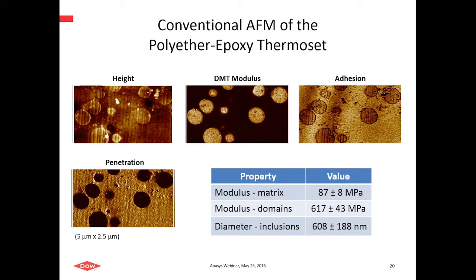In this particular system, we always supposed that these phase-separated domains were epoxy-rich because we expect epoxy to be the more rigid component in this system. But we had no way of confirming that chemically until now with the AFM-IR. We also see here even some inclusions showing perhaps some compositional variation within the domains, and we'll talk about that in a minute too.